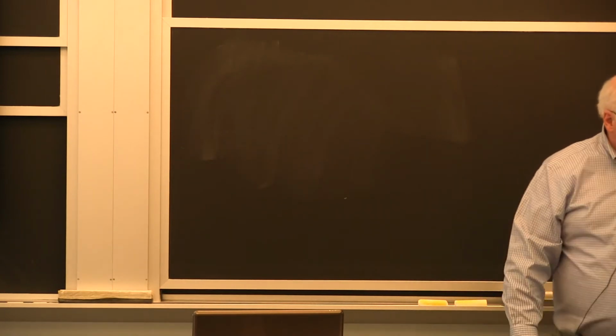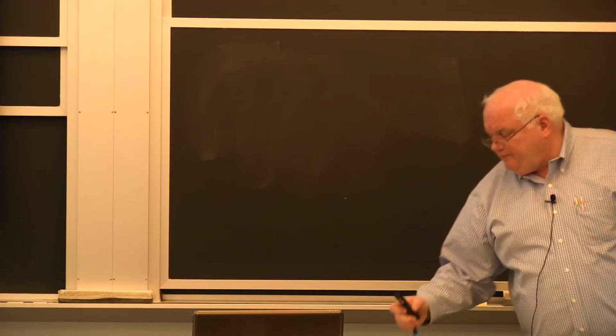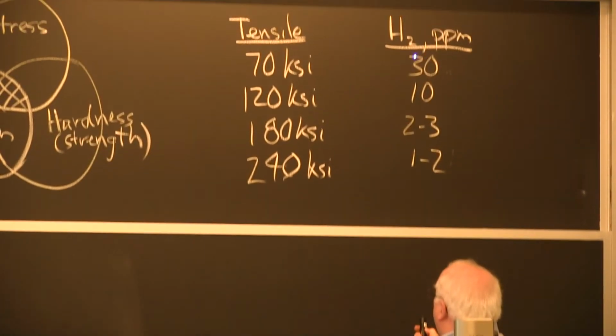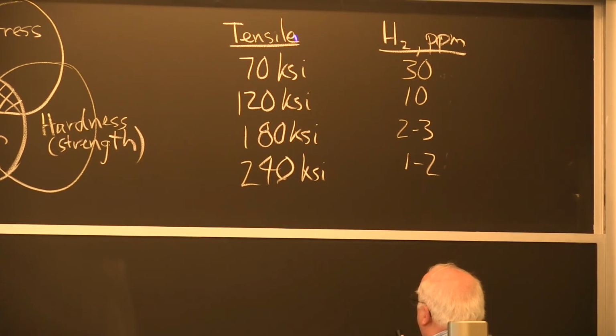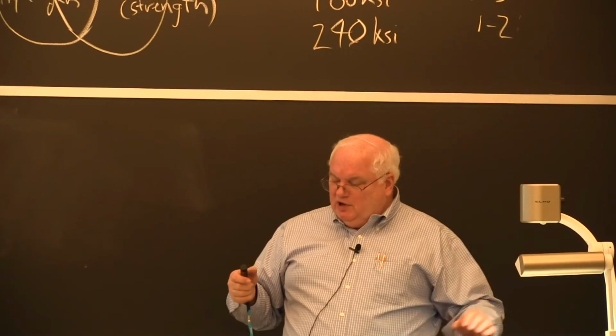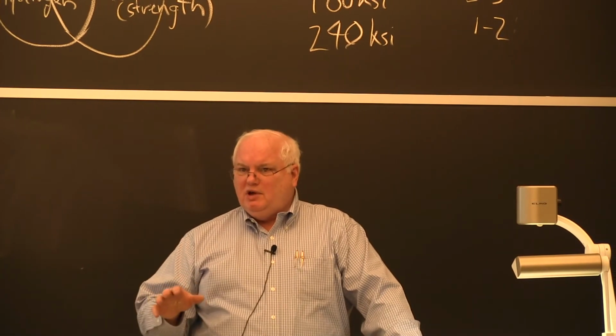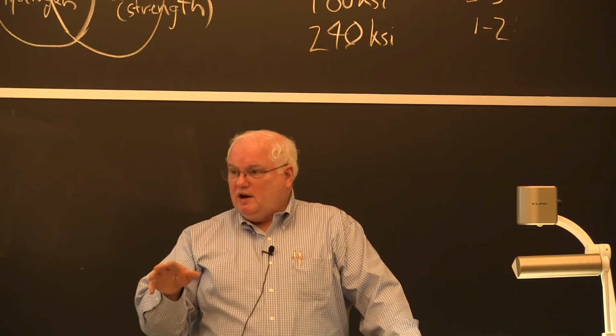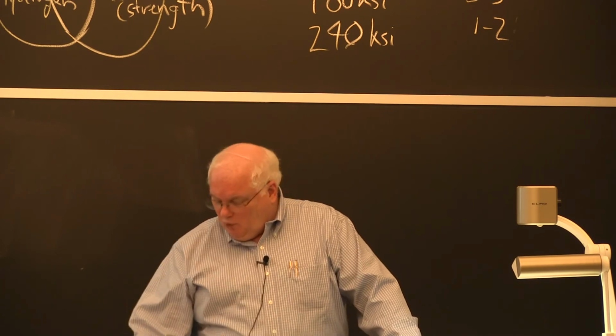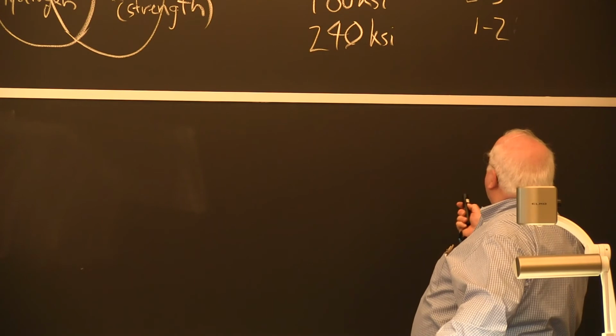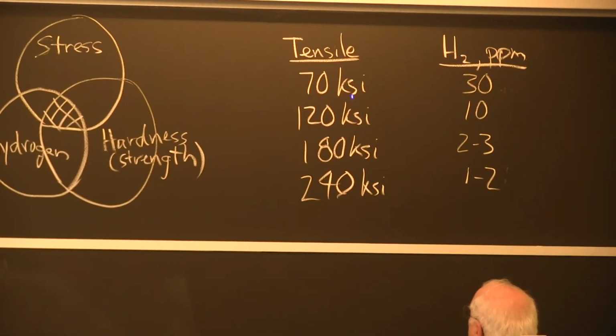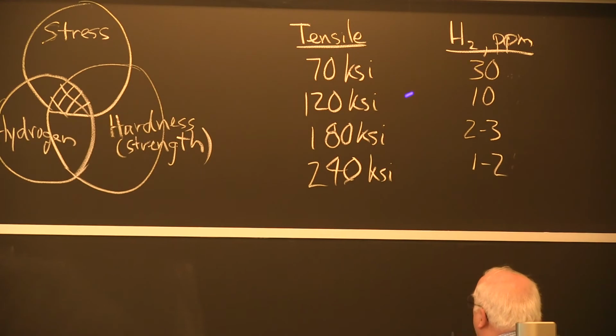Okay? I think I told you the other day that if I'm welding 100 KSI steel or 120 KSI steel for a bridge, versus welding a 70 KSI steel for a bridge, I don't really have to do much of anything. I'll show you what we have to do. With 120 KSI, I have to test that steel afterwards to see if I developed any cracks. I can't just weld it to my recipe and assume everything's good. I'm going to have to go inspect it afterwards at the higher strength level. Why? Because I can use almost any electrode with this steel and, with a little bit of care, I won't get enough hydrogen.